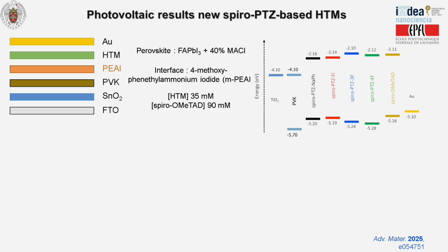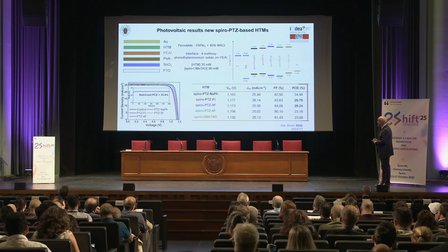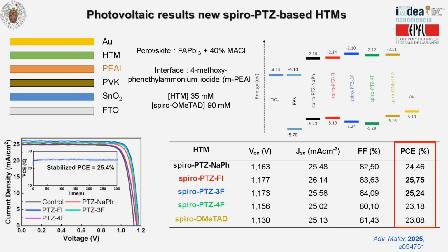Interestingly, in this system the perovskite was FAPI, so formamidinium lead triiodide, but the synthesis was carried out with 40% of methylammonium chloride. This is not to get a complex compound, because at the end the methylammonium chloride disappears from the middle and you get the same compound. But also the interesting thing here was just to introduce an interface, which is the methoxyphenylethylammonium iodide, which is here. And these are the typical features. So here is the concentration of our systems, 35 millimolar versus the 90 millimolar of the other one. So the quantity is relatively much lower. And this is amazing because these are the PCE values reported.